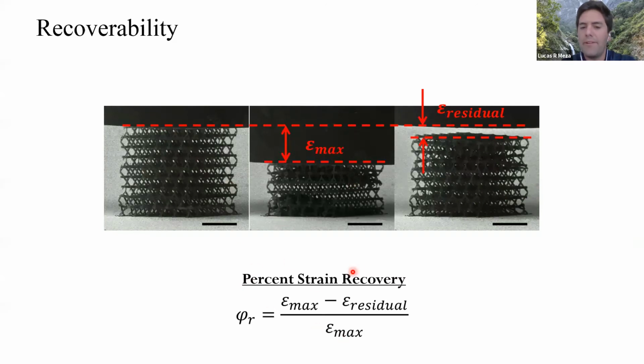We defined a figure of merit, percent strain recovery: maximum minus residual strain. If it recovers fully, you have a percent strain recovery of 100%. If it doesn't change at all, if the residual strain equals the max strain, you have 0% strain recovery. For example, this is 68% strain recovery.